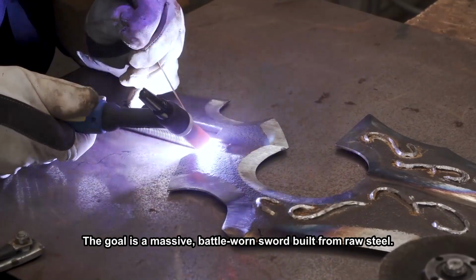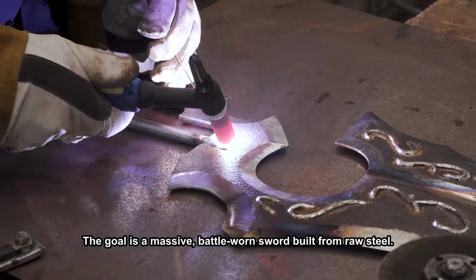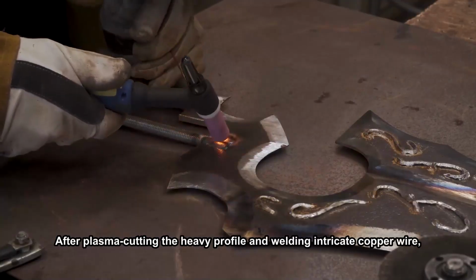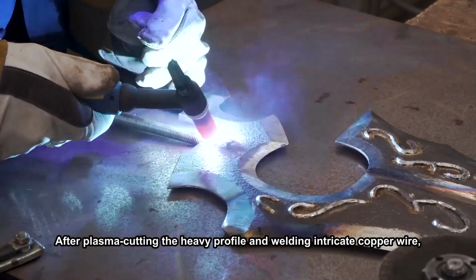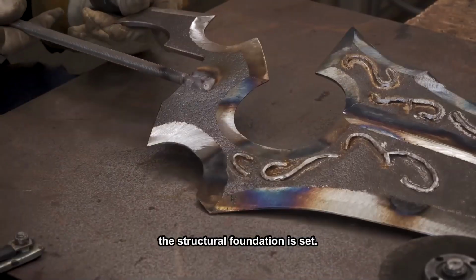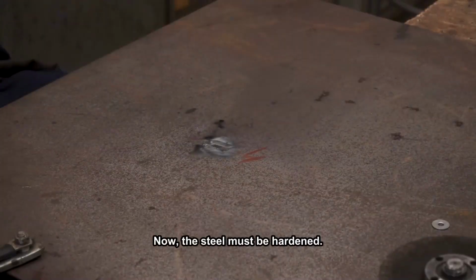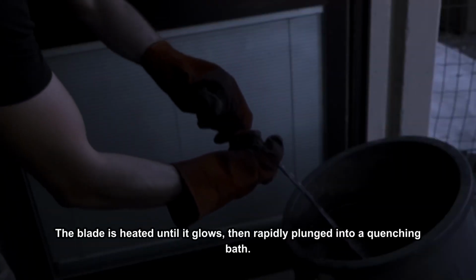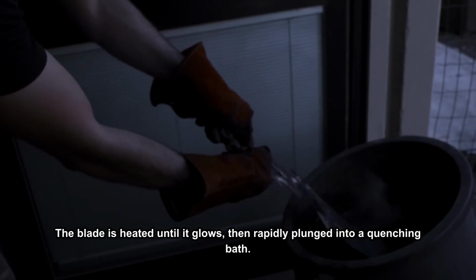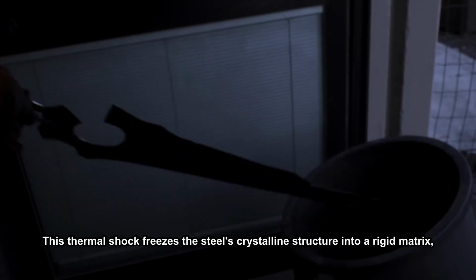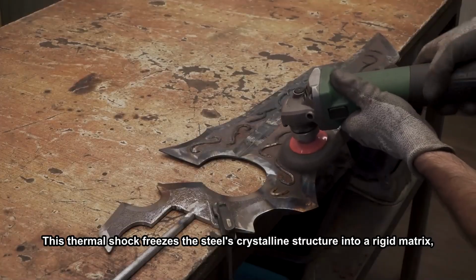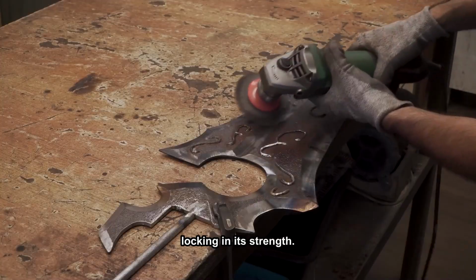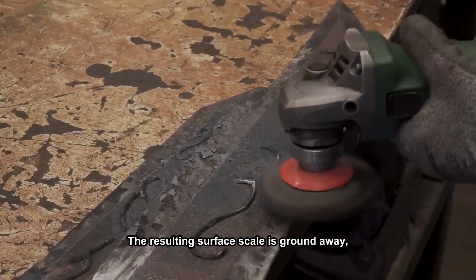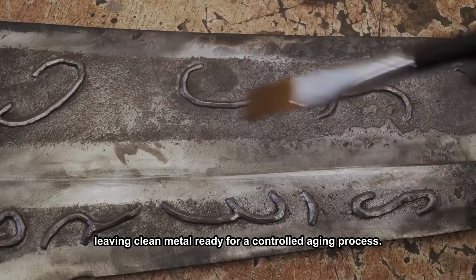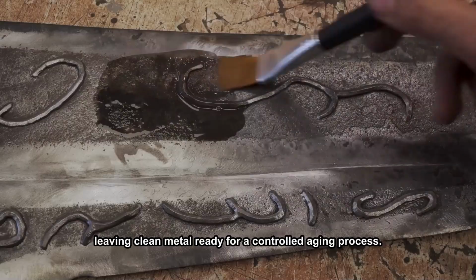The goal is a massive, battle-worn sword built from raw steel. After plasma cutting the heavy profile and welding intricate copper wire, the structural foundation is set. Now, the steel must be hardened. The blade is heated until it glows, then rapidly plunged into a quenching bath. This thermal shock freezes the steel's crystalline structure into a rigid matrix, locking in its strength. The resulting surface scale is ground away, leaving clean metal ready for a controlled aging process.